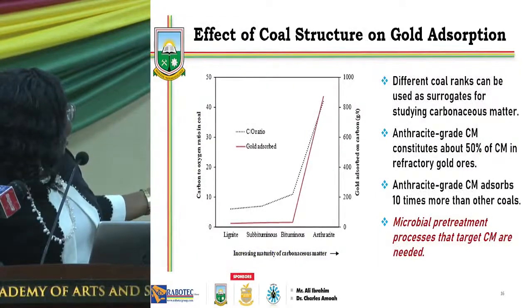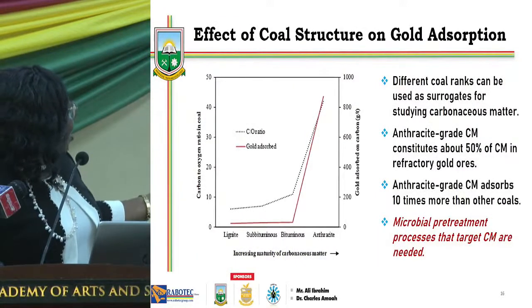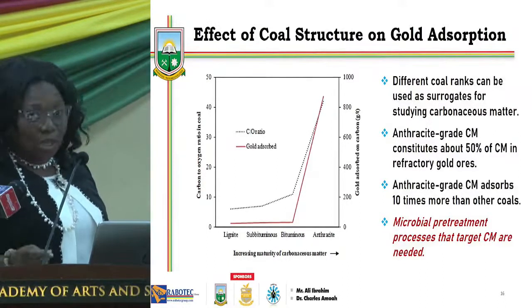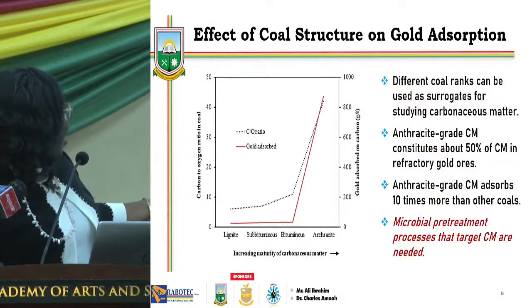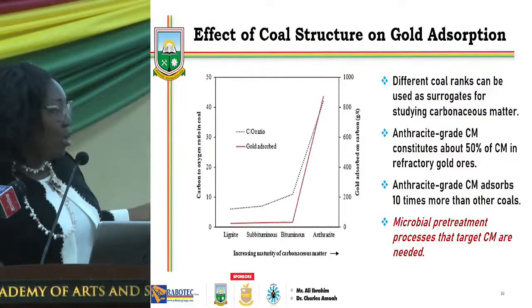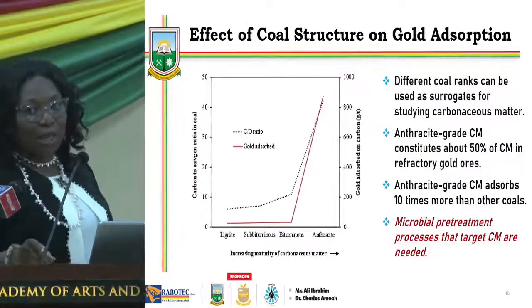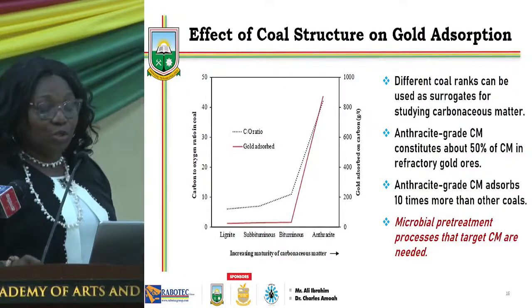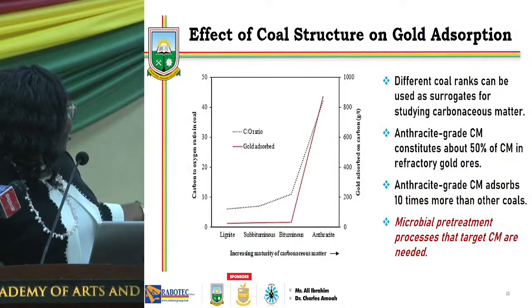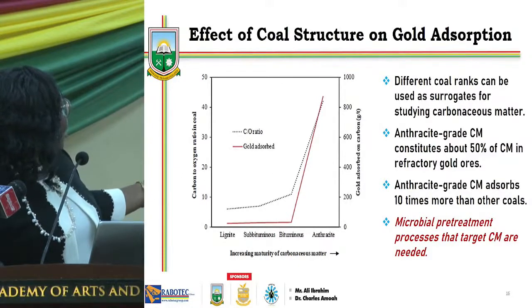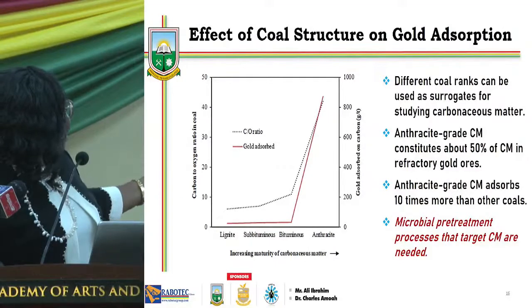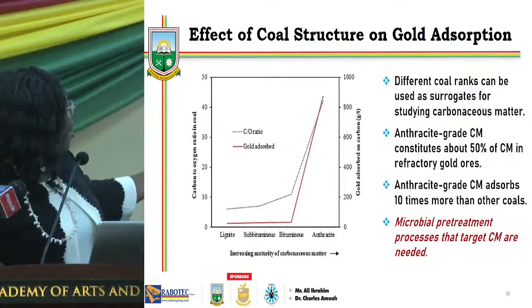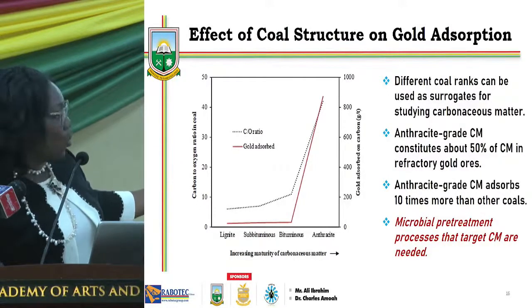Now we can look at this diagram too, to also reiterate the fact that the carbon structure, the graphitic structure, is important for gold adsorption. So here we have different ranks of coal. We have lignite, bituminous, and anthracite. And maturity of coal increases in that direction. So anthracite is the most mature form of coal. And contacting these coals with gold solution, we realize that the anthracite is able to adsorb more, far higher than the other ranks of coal.